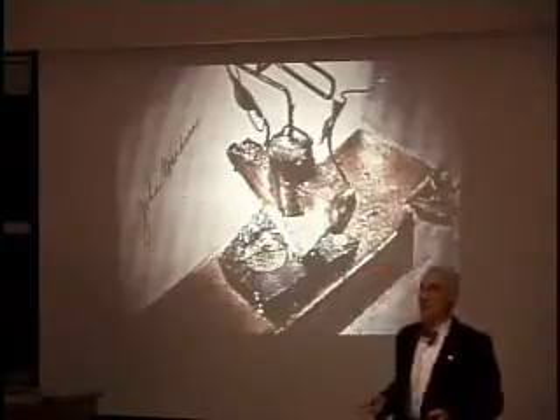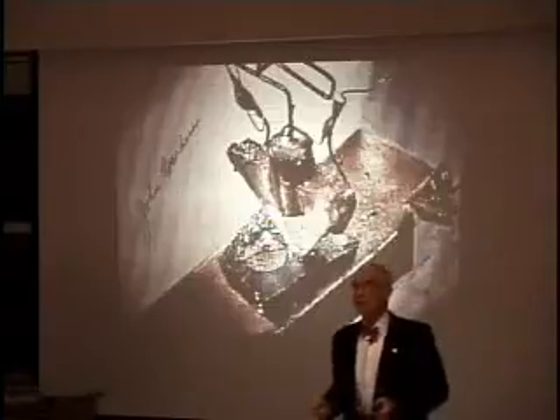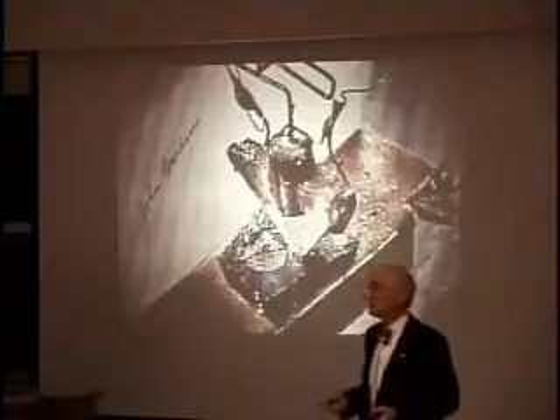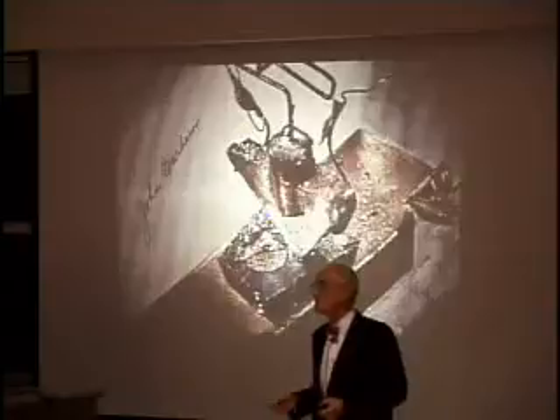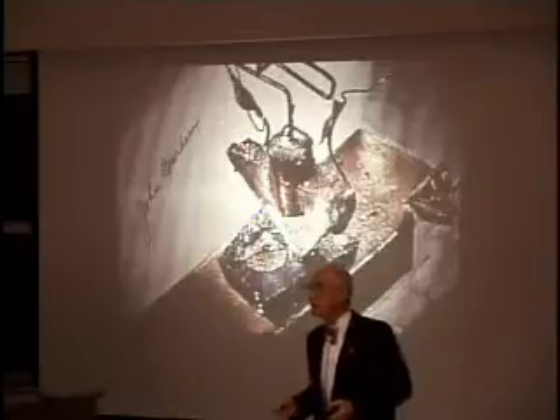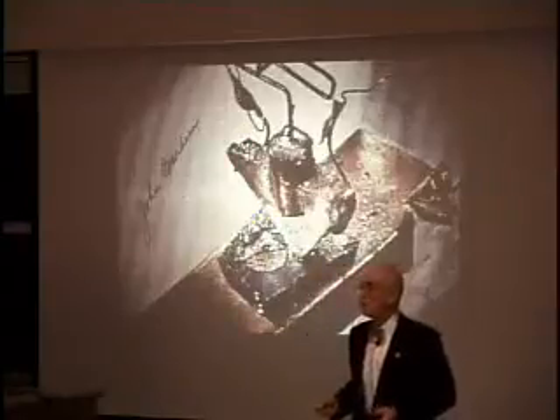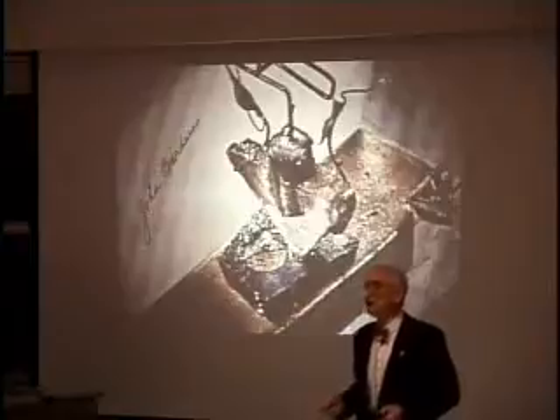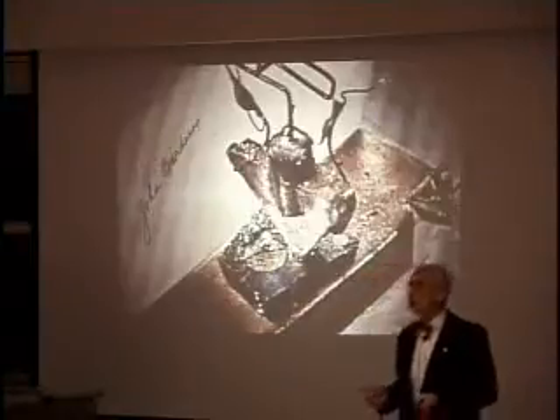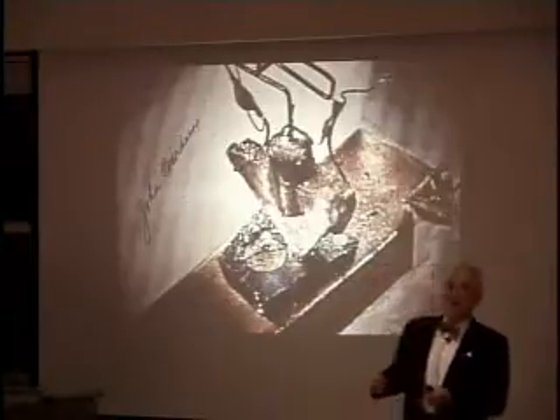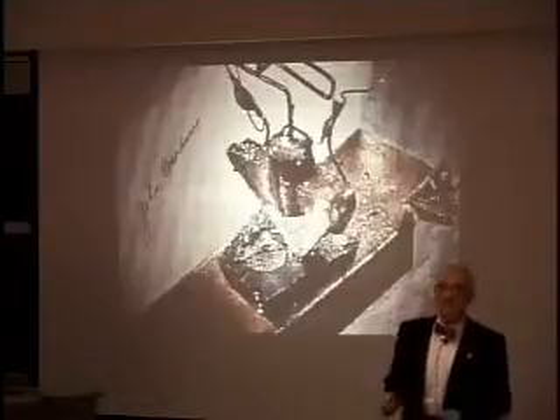What no one knew was that when the gold pad was put on the oxide, it would not be on an oxide. The oxide on germanium isn't all that good. They were in direct contact with the germanium. And they had an injection device. A signal on one of the electrodes gave a signal in the other electrode, and they realized what they had.